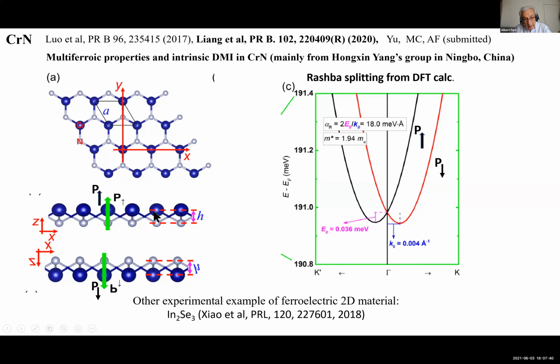And of course, these two structures have no inversion symmetry, and opposite electric fields in the two. So what can be expected? Opposite Rashba interaction in these two structures, and opposite DMI also in these two structures. And so the DFT calculation was performed to first check that there really is a Rashba interaction, and that the Rashba interaction depends on the direction of the electric polarization.